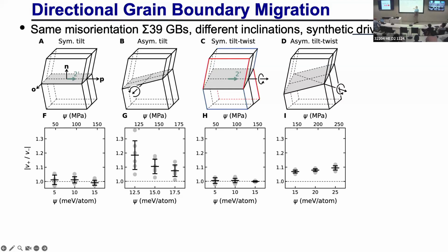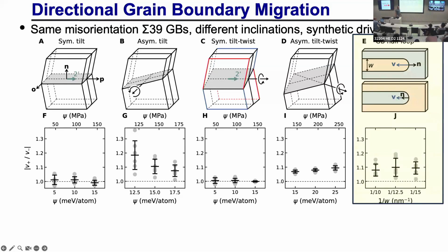It's a function of driving force. And this is another asymmetric boundary, again as a function of driving force. It looks like that. Okay, so symmetric boundaries have the same mobilities in the plus or minus direction. Asymmetric boundaries do not. And just one final case to look at is this situation.